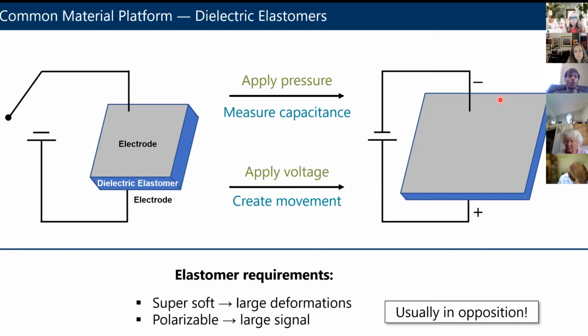Now, the requirements for that blue elastomer layer in between are contrary to each other. You can optimize one at the expense of the other. You'd like it to be really soft because both of these modes, either the pressure sensor or the actuator, rely on deforming that middle layer. But you also want it to be polarizable.